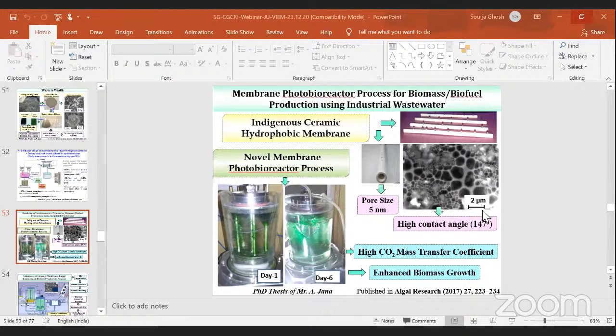Another part of our work is the membrane photobioreactor process for biomass and biofuel production using industrial wastewater. So this application demands hydrophobic ceramic membrane. So these membranes were indigenously developed for the first time in our country, and here you can see the picture of this hydrophobic ceramic membrane, which shows a high contact angle value of 147 degrees. And now we have developed a super hydrophobic membrane, which shows a far greater contact angle, that is greater than 150 degrees. And this membrane was used in a photobioreactor.